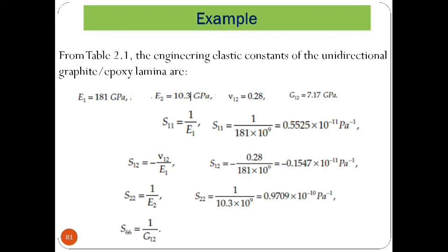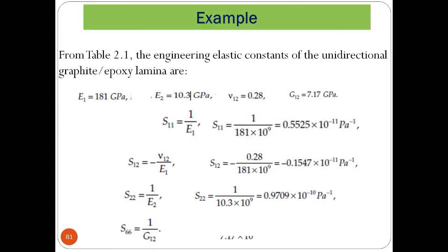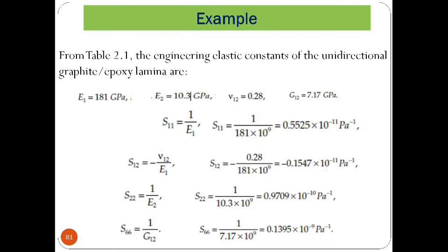Now similarly, S66 equals 1 over G12. S66 is dedicated to the in-plane shear stress. So this will be calculated as S66 equals 0.1395.